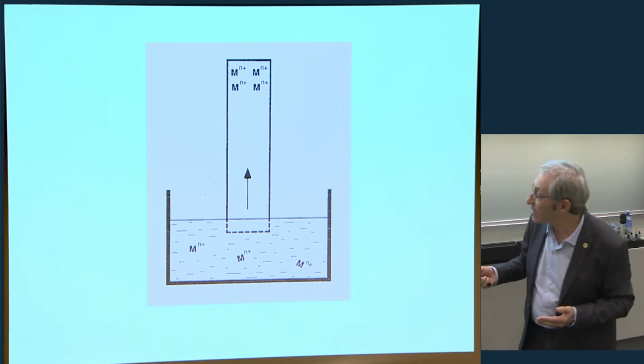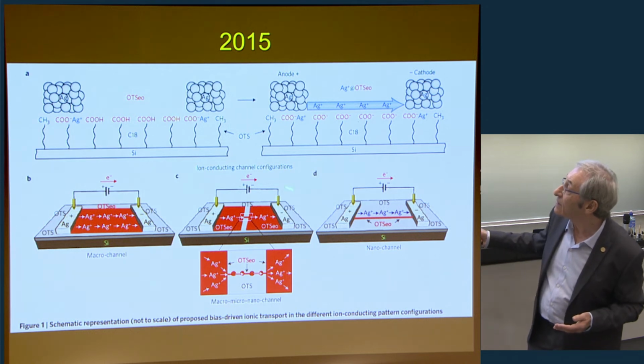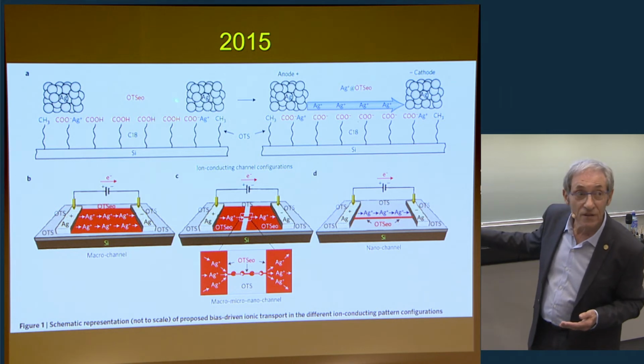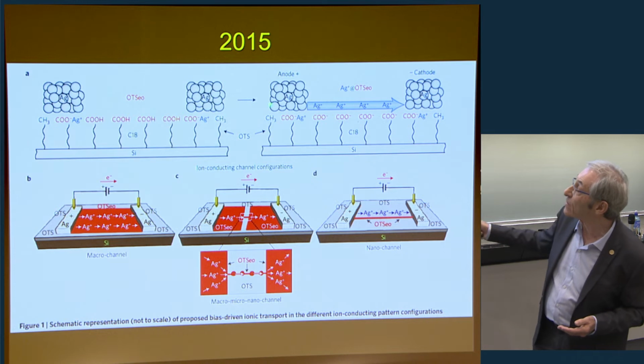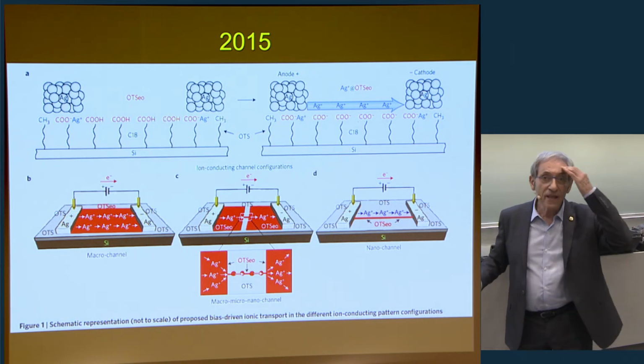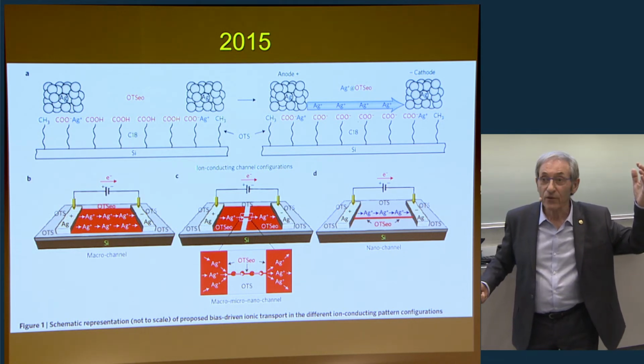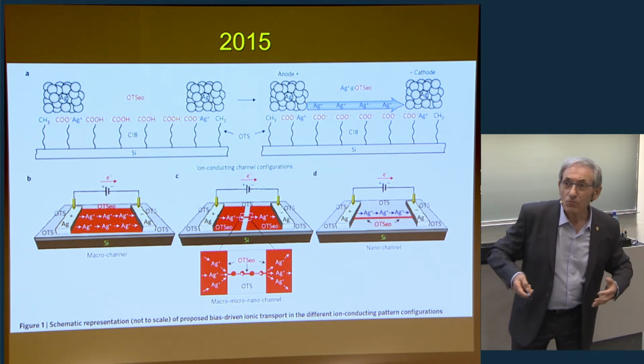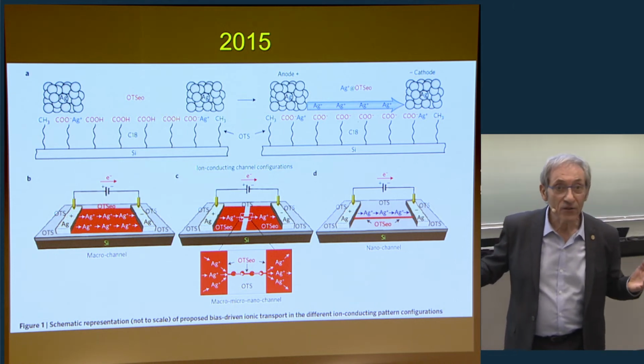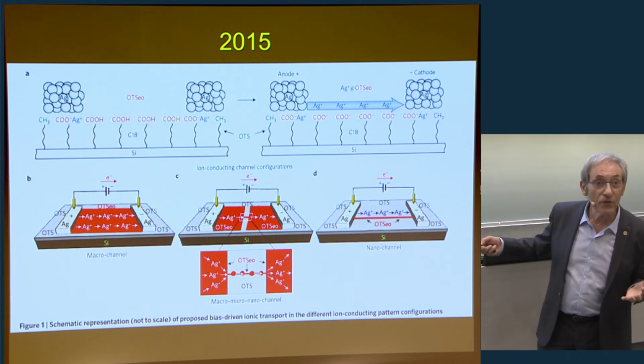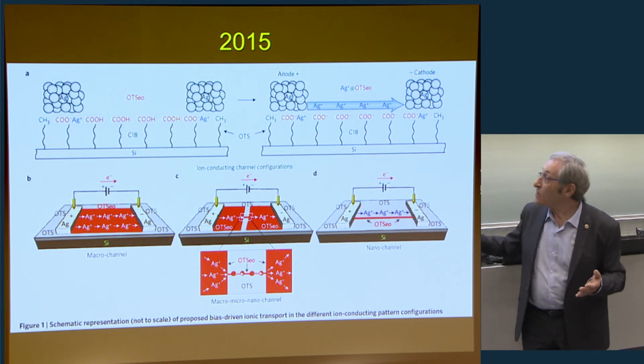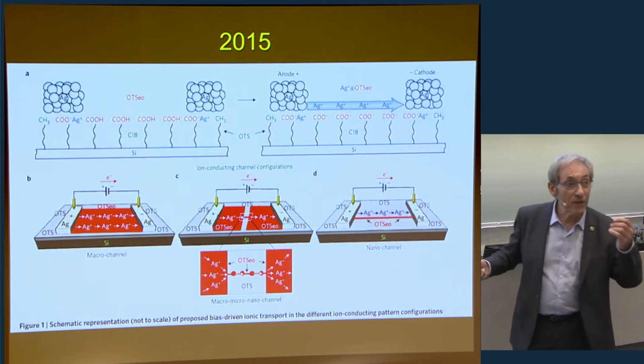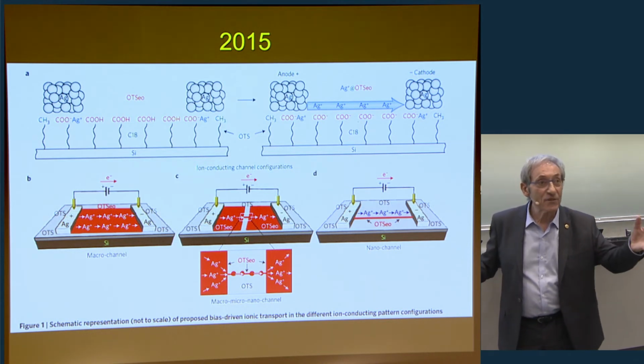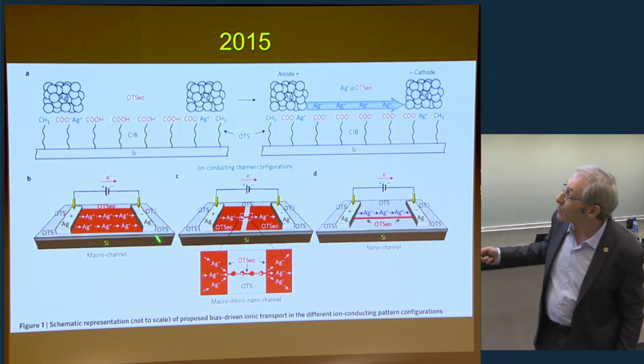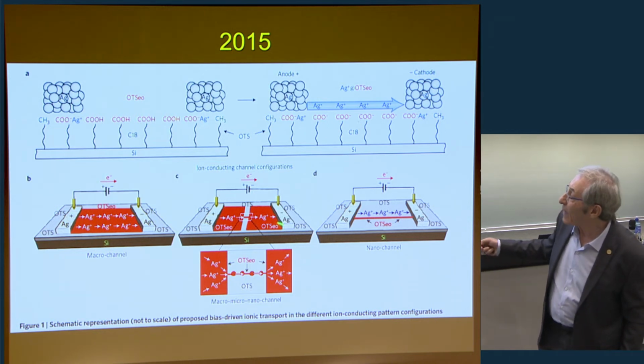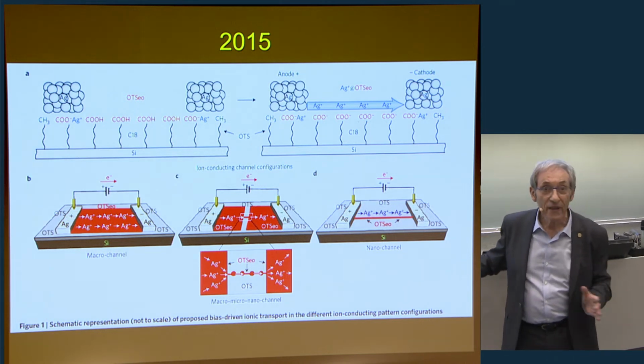And then the idea came that perhaps we can do this. We can pattern our OTS monolayer, place electrodes, apply a bias, and eventually see whether we can replace protons and move ions laterally. And the idea was that we are going to make ionic circuits, nanocircuits. So you know, in the living organism, most of the electrical events are not electronic, are ionic. But nobody did anything artificial where you can move ions in a controlled manner on a surface. So the idea was to make circuits, and we could pattern with the AFM tip. Then we developed the possibility to pattern with stamps, so actually with electrical stamps. So actually it was possible to make macro channel structure, to make micro, and to combine them. It means you can do anything you want in this way, and the ions should move.